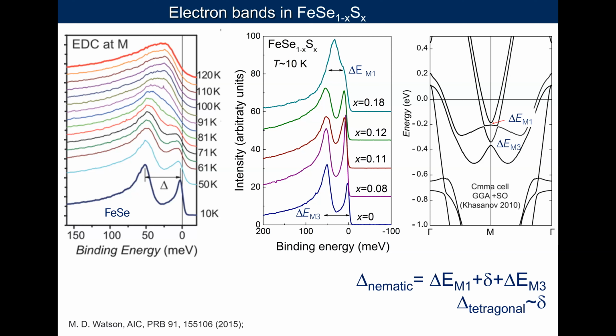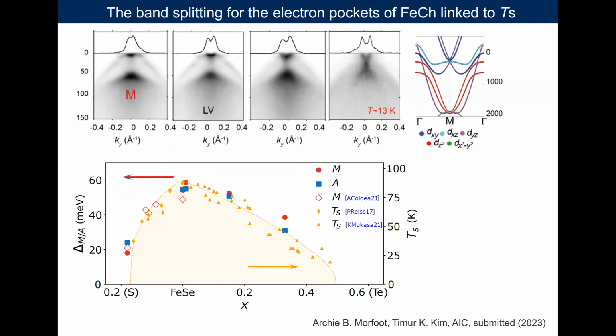But the final splittings also exist in a tetragonal phase. So if you put all this information on the phase diagram, we see that this kind of quasi-splitting, which occurs for the electron pockets, is strongly linked to the transition temperature of the system. So obviously, it has a strong link with nematicity and potentially with the lattice effects as well.